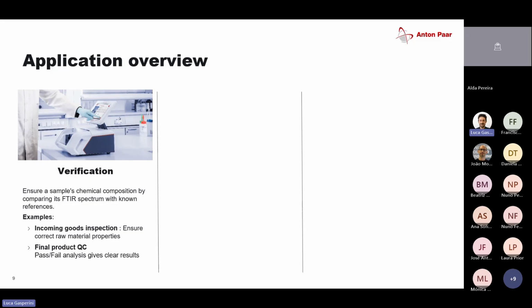What you can also do is, let's say you produce your own polymer formulations, and you want to get an idea if the formulation has the right composition, if it is the same as your gold standard, for example. So you have your reference, then you would compare the freshly produced batch with your reference or gold standard to get a quantitative idea or a verification.